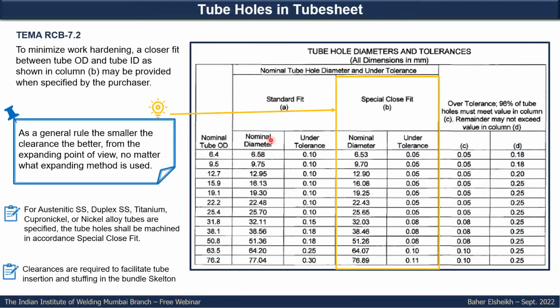Now, one factor that also contributes to how the tube will be affected under the expansion is how much gap or clearance there is between the outside diameter of the tube and the tube hole. In TEMA, there is standard fit clearance or special fit clearance, and it is highly recommended to have the special close fit clearance, where there is a minor or small gap between the tube and the tube sheet hole, so that you won't have more plastic deformation in the tube while applying the expansion.